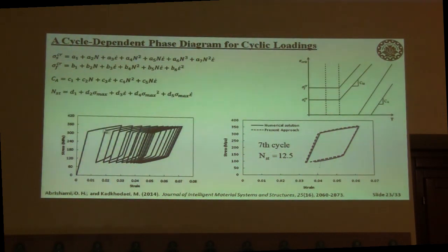For example, in such a loading, the number of the stabilized cycle is 13. Before simulating all the cycles, I can obtain with the use of these relationships N stabilized equals 12.5, meaning it is almost equal to 13.